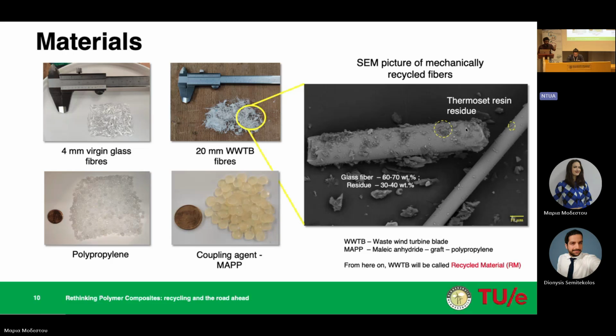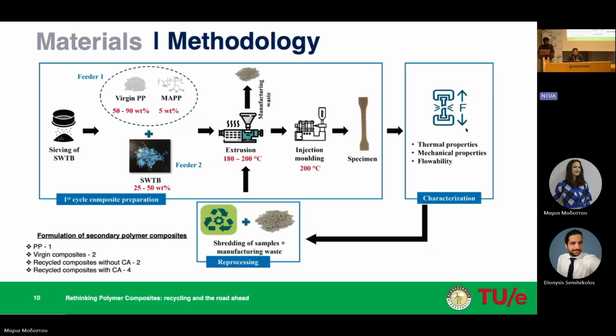Also, one of my colleagues asked a question about the size of the fibers. So in this research, I've used around 20 millimeters, or let's say below 20 millimeters, as the size of these fibers. And this is a simple methodology which I've used to produce the secondary composites and reprocess them. At first we did some sieving of these materials, which we received from Pre-Zero, one of our project partners, and we have used the coarse fraction of the wind turbine blade waste, which would have a size fraction between 5 and 20 millimeters.